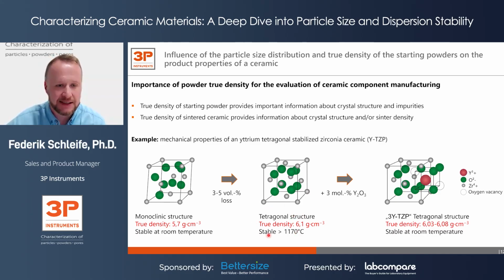So to get it stabilized also at room temperature, a mole percentage of yttrium oxide is typically used. And with this yttrium oxide stabilized zirconia modification, we can achieve that this modification is stable at room temperature. So by stabilizing the zirconia crystals with yttrium oxide, you will achieve a way more stable tetragonal structure at room temperature, which results here in a true density of 6.03 to 6.08 gram per cubic centimeter.